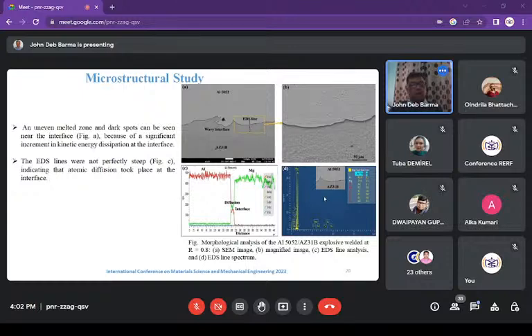Now here, if we talk about the EDS line, it indicates that the atomic diffusion, because you do not see a perfectly steep curve here, right? So it's not very much steep. So it means that atomic diffusion took place at interface, and the occurrence of the atomic diffusion in the explosive weld is very much consistent with the prior studies that have been done by different researchers.